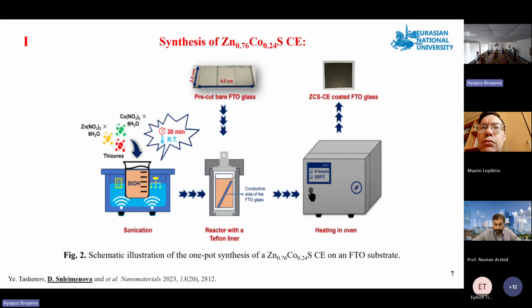We have performed a solvothermal synthesis of zinc cobalt sulfide counter-electrodes. Zinc and cobalt nitrates with thiourea were dissolved in ethanol and sonicated at room temperature. The resulting mixture was transferred to an autoclave with the FTO substrate and heated. After cooling, the electrodes were washed and dried in a vacuum oven.